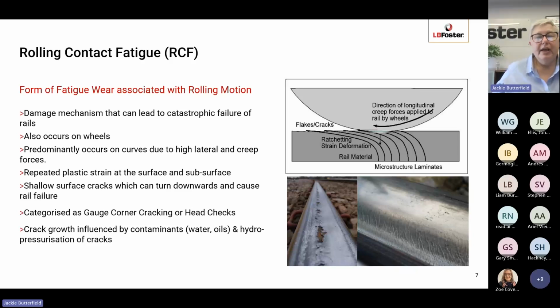So we have head checks in the left picture where the material is actually delaminated and spalled off. So these shallow cracks have joined together and then resulted in a loss of material from the head of the rail. And then we have the gauge corner cracking in the right-hand corner. So you can see a pattern of very, very fine diagonal cracks on the corner of the rail. And these are the rolling contact fatigue or RCF cracks.